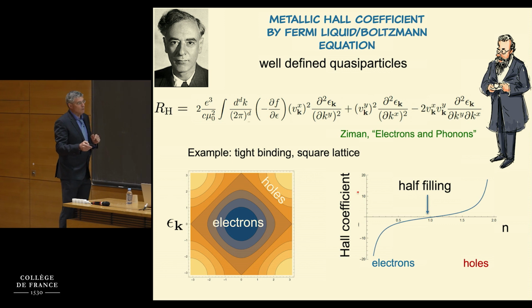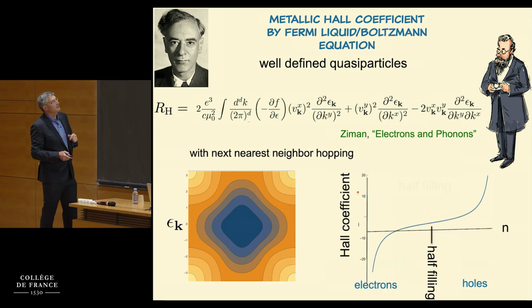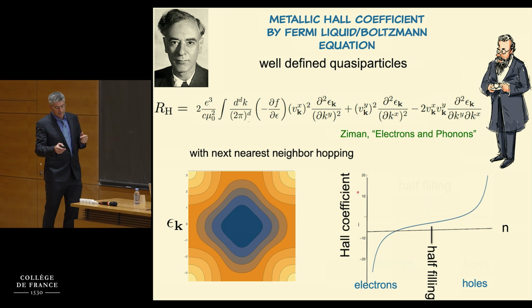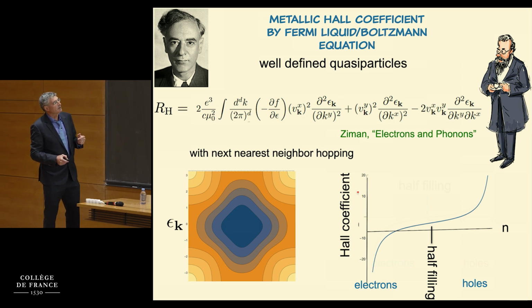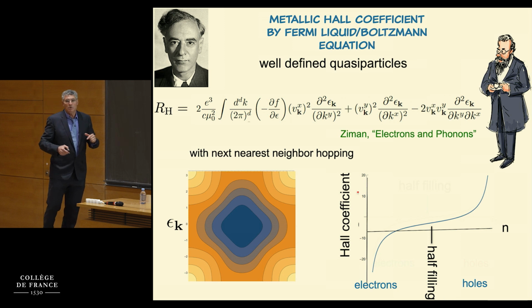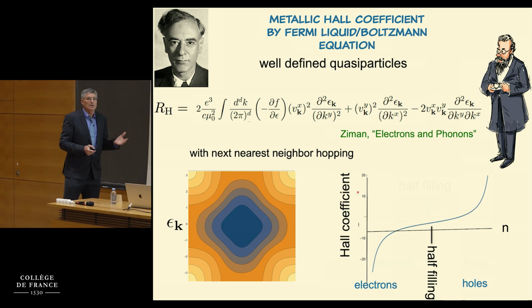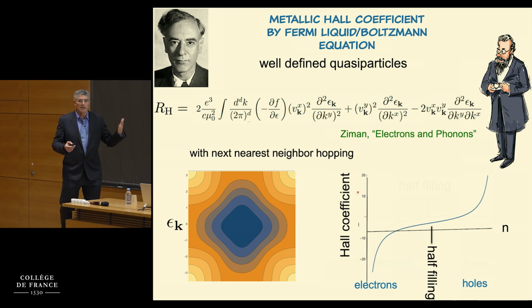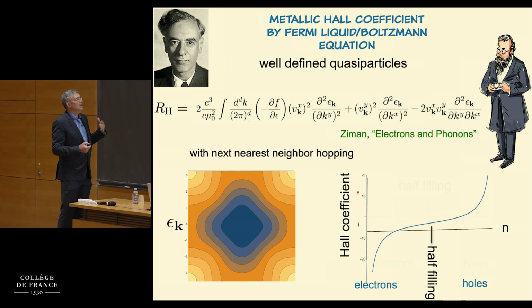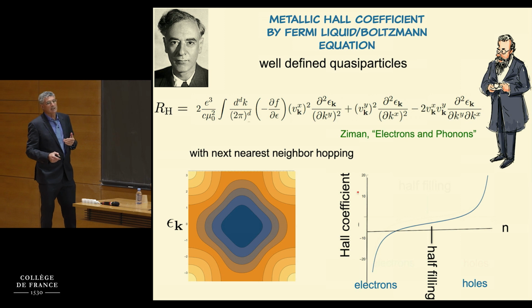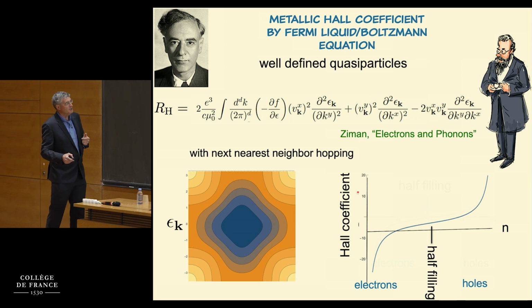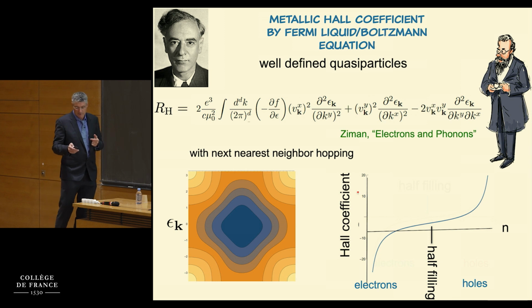So once you see this, and this is with next nearest neighbor interaction, what the next nearest neighbor interaction does is move the zero crossing from half filling to the left or the right, depending on the sign of the effect, because you can see the curvature, even at half filling, is negative in most places. So this is the well-known result that everybody uses, and it is modified by adding scattering rates that depend on k, but the absence of singularity in the band is a general property of Fermi liquid theory.